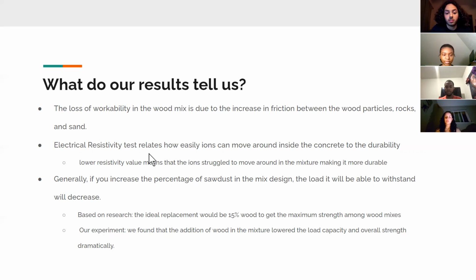Both samples, in fact, allowed a high penetrability level of chloride ions, but the 5% wood mixture was slightly less than the base mix. Since the ions were not able to move as freely in the wood mixture, the concrete cylinder showed an increased resistivity, which directly correlates to an increased durability. When we talk about durability, it means that this concrete cylinder will be able to perform and withhold the properties of the design over a longer period of time and under harsher conditions.